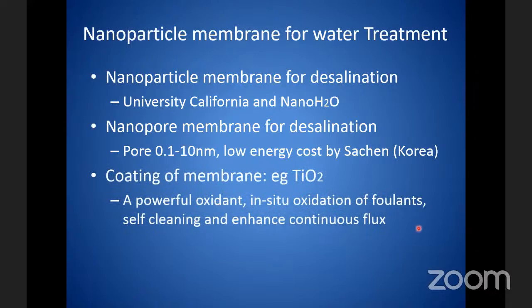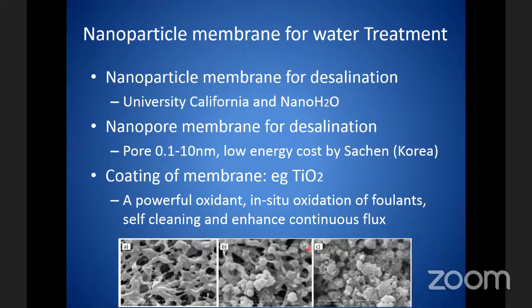So another method is to coat the membrane with titanium oxide. This is an example of coating with titanium oxide. So titanium oxide is a very powerful oxidant. So it can oxidize the foulants in situ. It will become self-cleaning and enhance continuous flux. So you see in this picture, on the left-hand side, this one is the original membrane. So they start to put in the coating, and then the membrane surface will be covered with this titanium dioxide. So before the pollutant can blind or foul the membrane, block the membrane pore, it will touch the titanium dioxide on the surface of the membrane, and then it will get oxidized, become a much smaller particle, if it is still there.